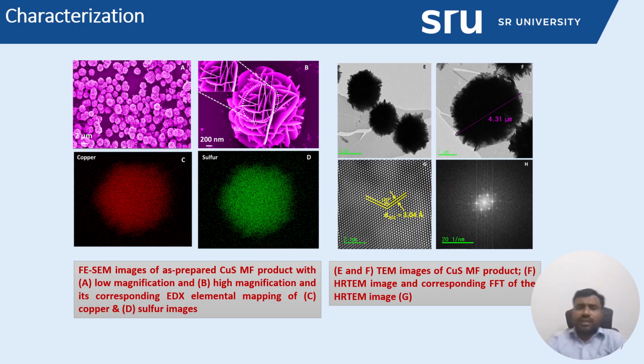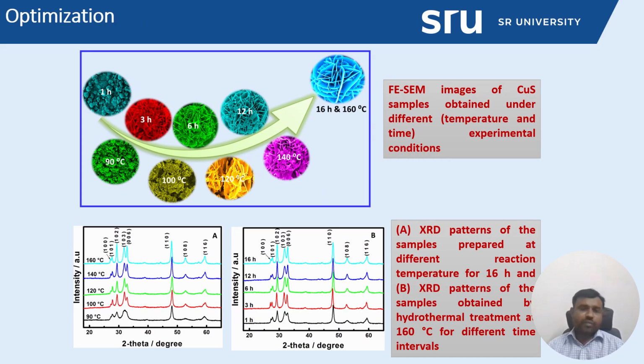So from this SEM, TEM and HR-TEM study clearly confirm the successful formation of copper sulfide without any impurity. Further, the crystal structure was confirmed by the XRD. This is the XRD spectra. So we have to achieve this, because we used 16 hours and 160 degrees. So we have to confirm the temperature as well as time.